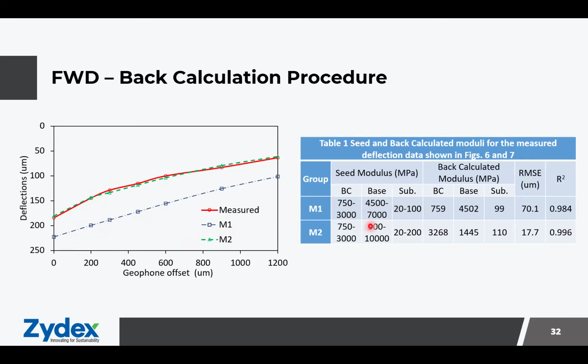Therefore, we need to either reiterate this modular value, or even consider a better range of other layers so that we have a proper convergence. So I'm showing another set of seed moduli, for the BC layer the same modular range, but for the base layer, we have given a very broad range of seed moduli from 500 to 10,000 MPa.